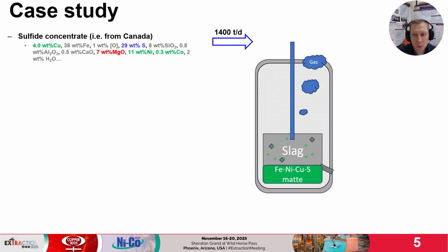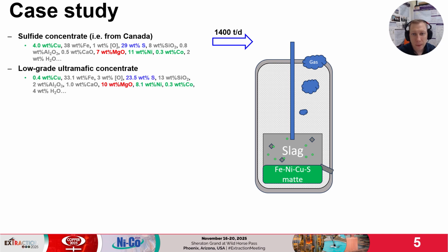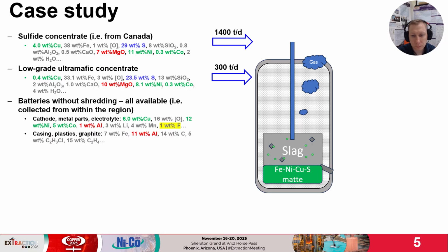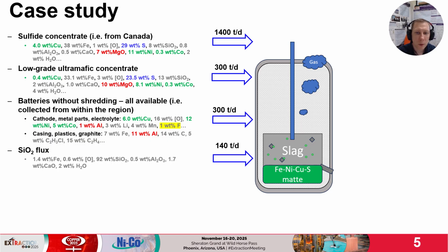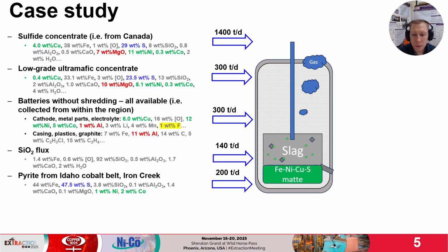The main input is a concentrate typical for Canadian smelters. The moisture content is higher compared to flash processing. The second feed is a lower grade concentrate, which is also high in MgO. The next feed is unshredded batteries. They contain cathode metal parts but also still have casings, plastic and graphite. In this process, nickel, cobalt and copper are recovered. Everything else burns into gas or goes into slag. We still use silica flux. Then we can feed the pyrite containing nickel and cobalt. It actually plays an important role bringing iron into the system, which I demonstrate in the next slide.